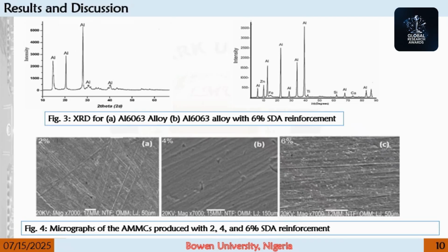Now, going to the results and discussion of this research, the XRD in Figure 3 displays that of the unreinforced alloy and the alloy reinforced with 6% SDA. The XRD pattern displays the various phases present in the AMC for the samples. It can be observed that the phase present is that of an aluminum cubic crystal system with only aluminum phases and peaks. That is for Figure 3a, the unreinforced alloy. The presence of peaks aside from aluminum in the reinforced composite was due to the introduction of the SDA particles. The elements at the peaks of the XRD are strengtheners. Those are the silica, the titanium, and other ones, calcium. They are strengtheners.